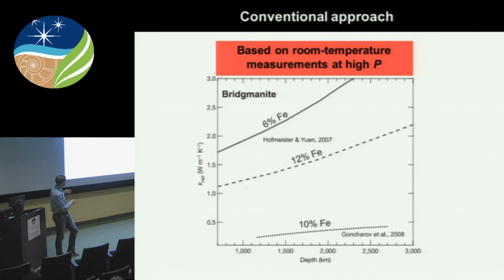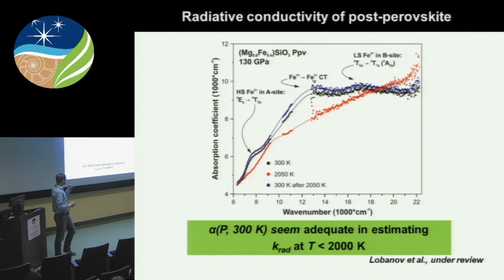The conventional view of the radiative thermal conductivity is based on room temperature absorption measurements in diamond anvil cells as a function of pressure. So you basically extract absorption coefficients, insert them in the K-rad formula, and you end up with values of radiative conductivity as a function of depth. There is a lot of disagreement, as you can see. But what these measurements agree upon is that radiative conductivity always increases with depth.